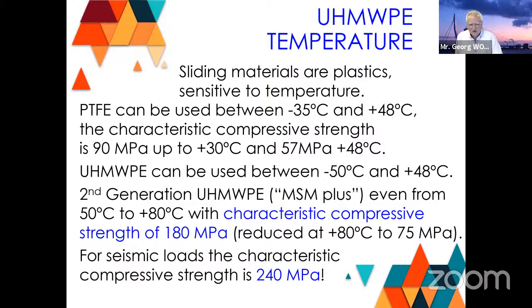But the ultra high molecular weight polyethylene can be used between -50 and 48 degrees in the first generation, the first tests. But some short time ago, I think around 6 years, a second generation was developed. It's called MSM Plus, and here you can even use it up to 80 degrees Celsius, with a characteristic strength of 180 MPa. You compare that, it's double what you have in the PTFE, and at 80 degrees it's reduced, but it still carries 75 megapascal. And this system for seismic load even can take a compressive strength of 240 megapascal. So that's really a big step.